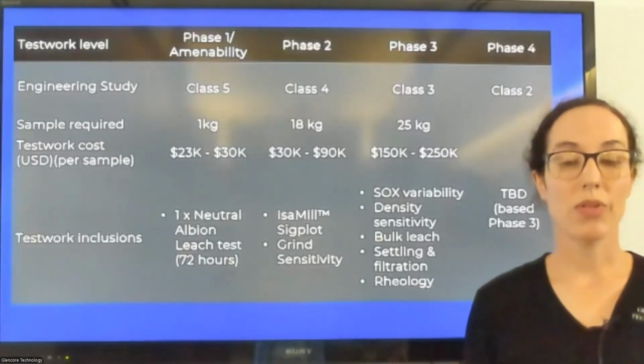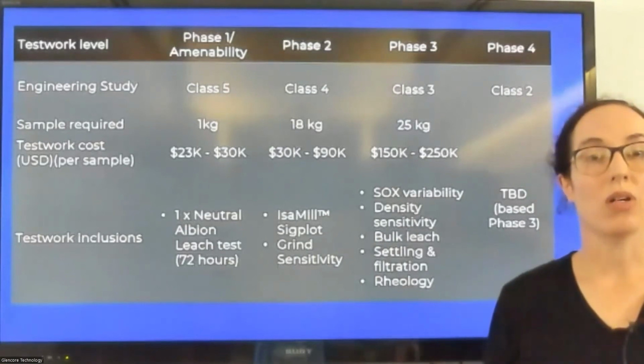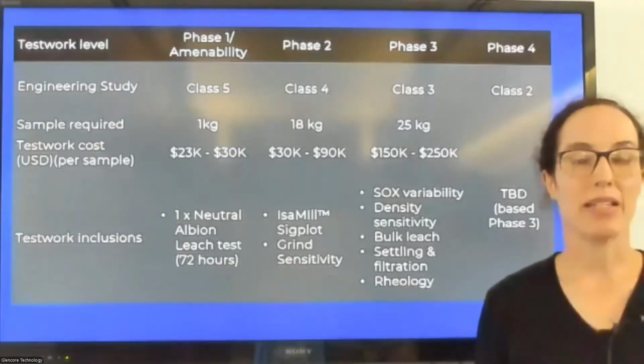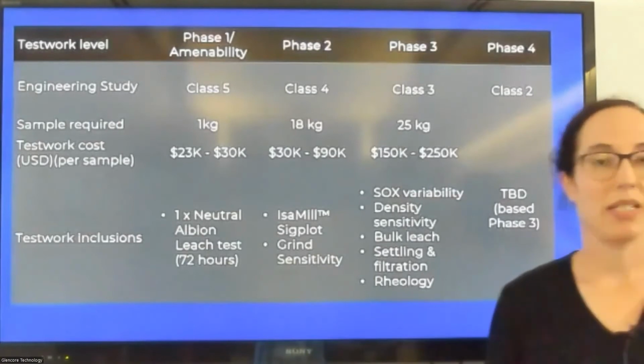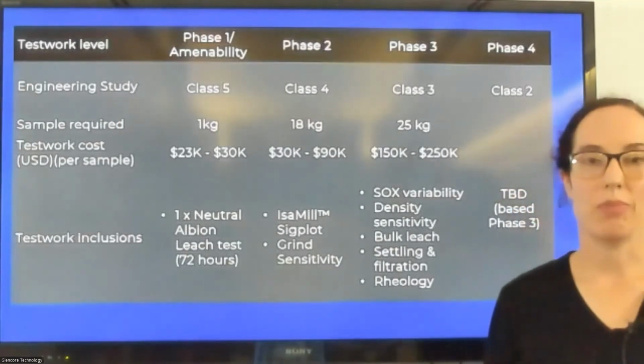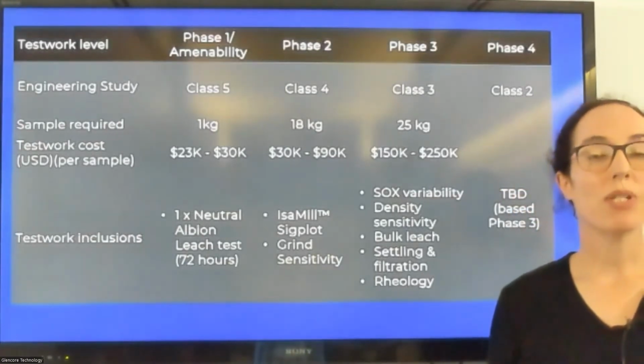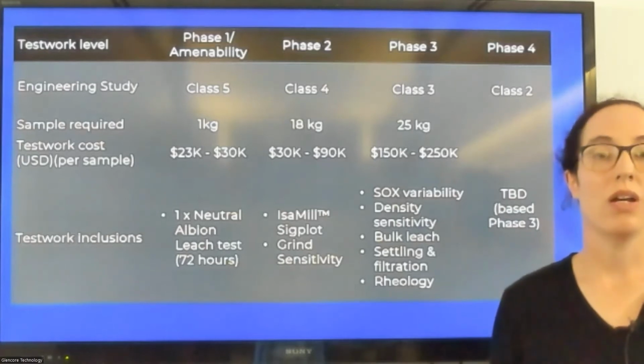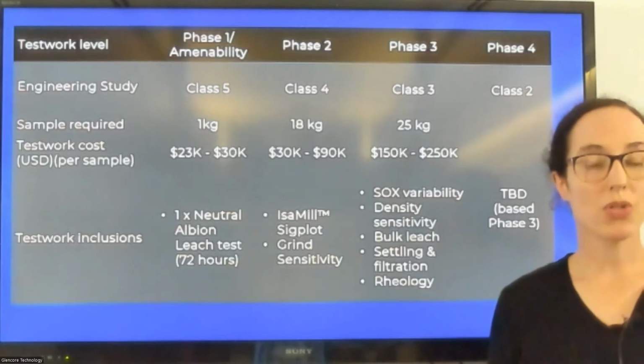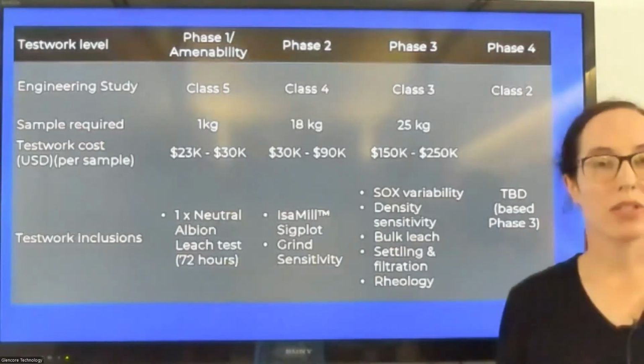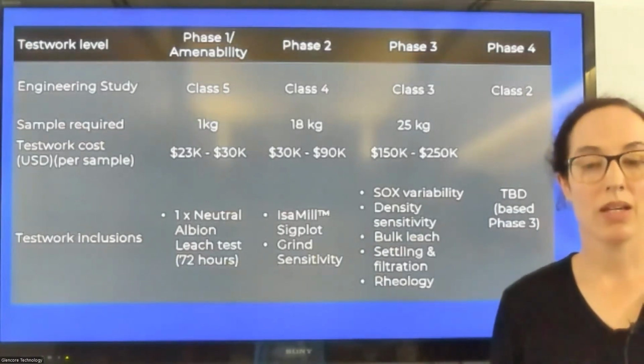With the SOX variability test, we also then look at the density sensitivity. In the amenability test, we ran the test at 15% solids. There is always potential to run the test at maybe 30 or even higher percentage solids, which will reduce the size of reactors and reduce the capital expenditure for you.